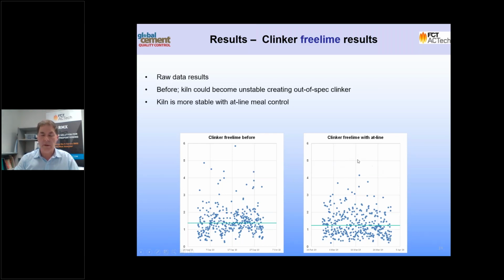So it's showing that the analyzer has helped stabilize the kiln. The average free lime is now a little bit lower, but it's still within an acceptable range, and they're able to run at this higher C3S level. So the plant has been able to use this increased kiln stability to increase their C3S target, which will in turn give them more strength, while only reducing the free lime slightly.